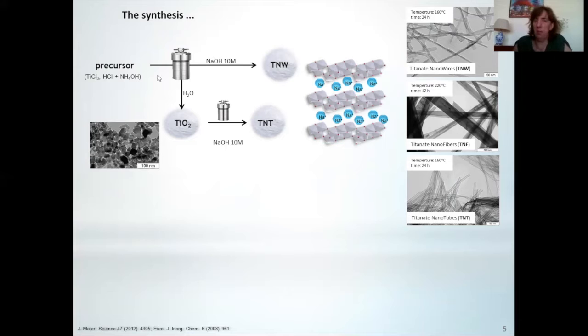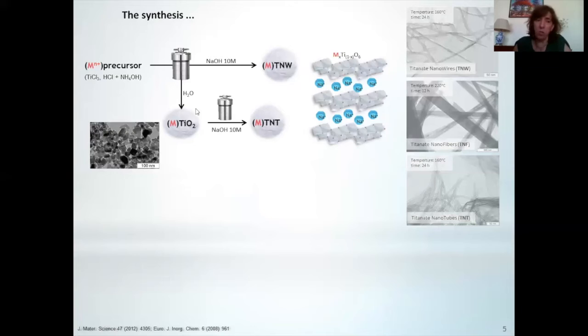But this is how to prepare titanate nanowires or nanotubes, and we want to modify these structures. So if we decide to add a metal when we are preparing the precursor, in the end we will have a doped precursor that we can use exactly in the same way to prepare doped materials. In this case, depending on the amount, we are replacing some of the Ti4+ by the metal in the octahedron, okay?